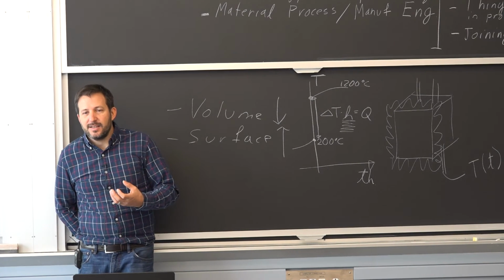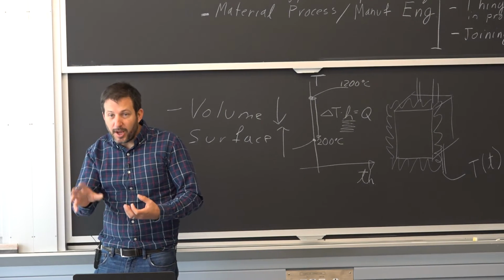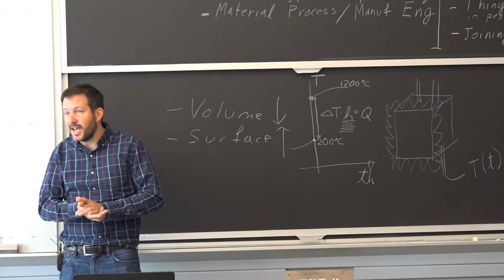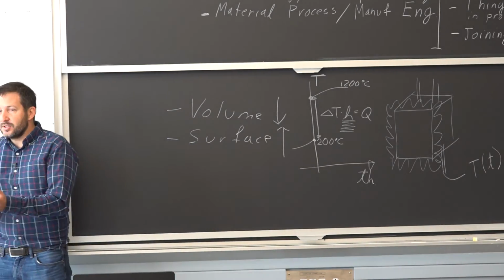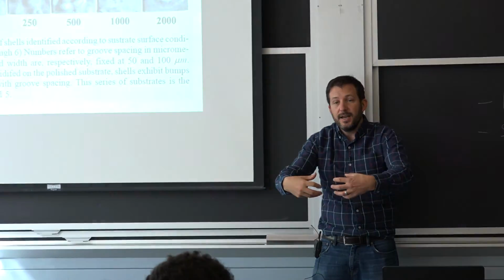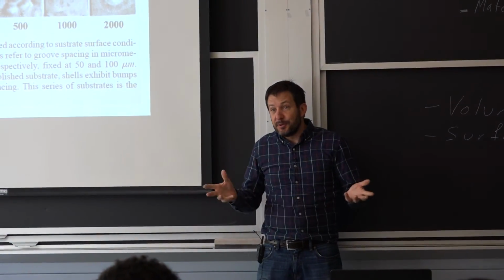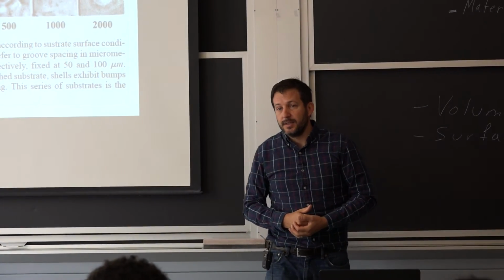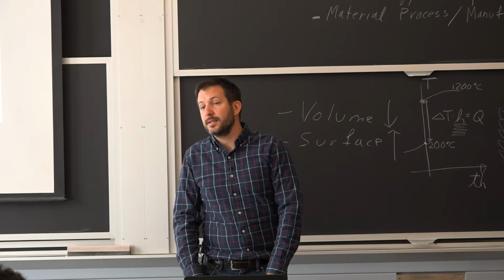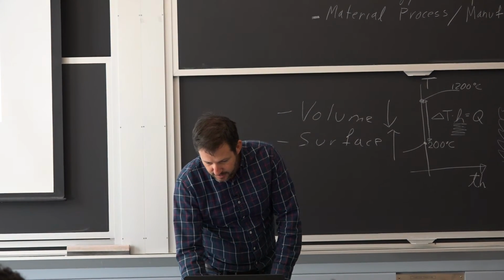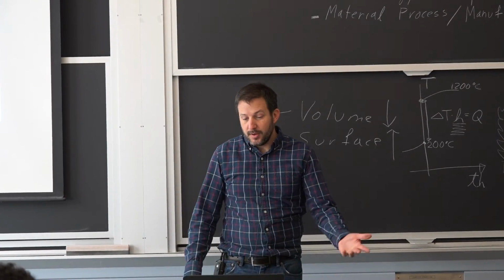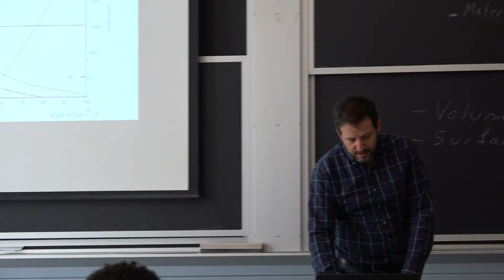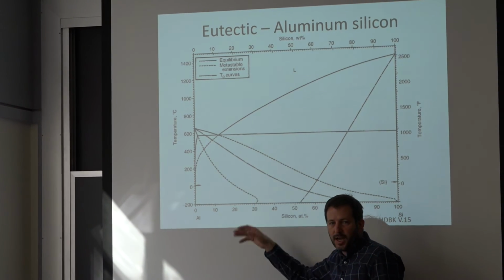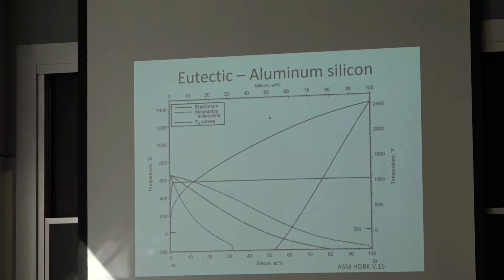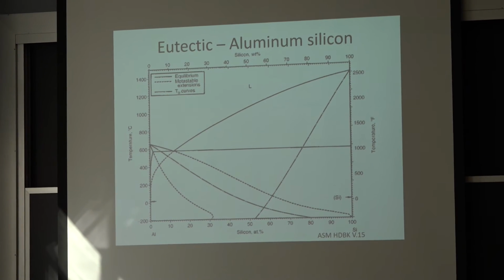So in the case of die casting, the fact that you apply a pressure, just that itself helps you keep that contact constant. So if this sheet is trying to rip off, there's a fluid pressure behind it that forces it to touch. It's one reason why a pressure casting is a better process than just gravity casting. All right. So we want to avoid those, and we talked about the fact that we want alloys because it's a lower melting point than it is to have the pure metal. I've also mentioned that it allows you to get very intricate into the microstructure.